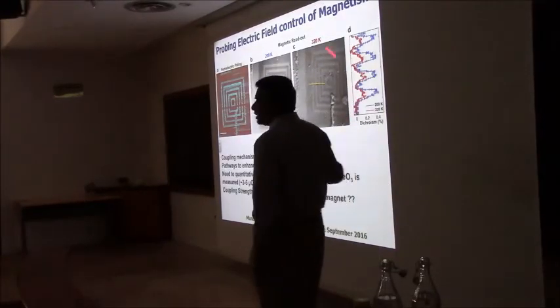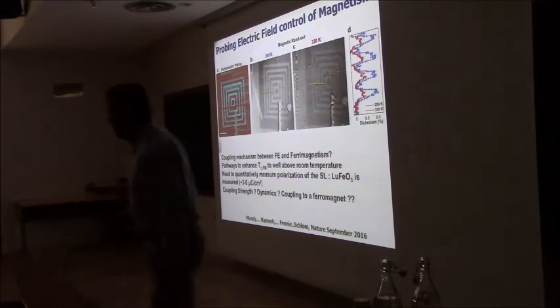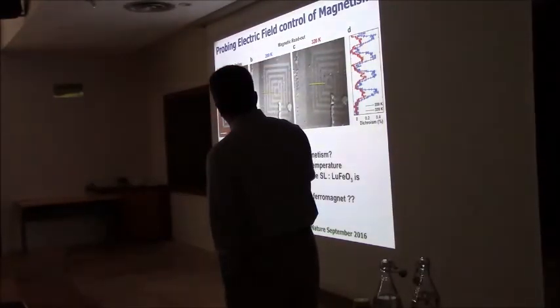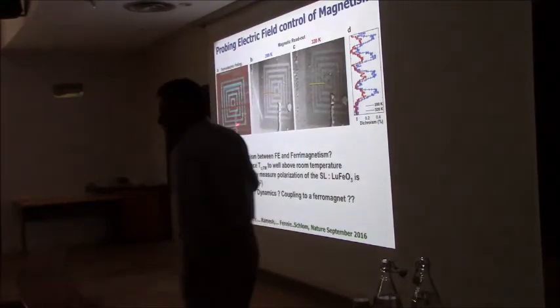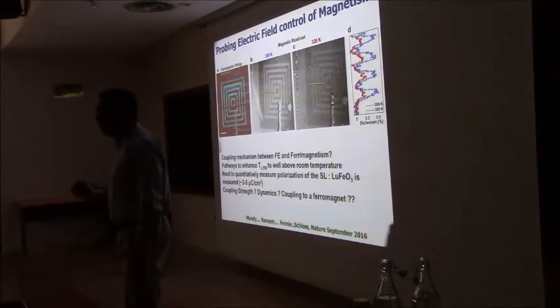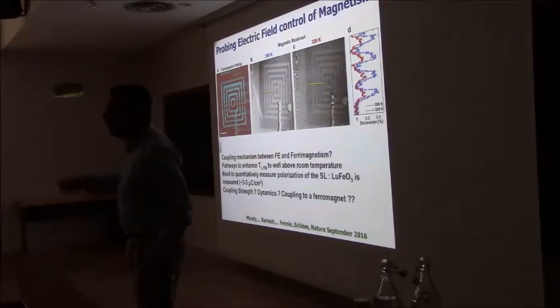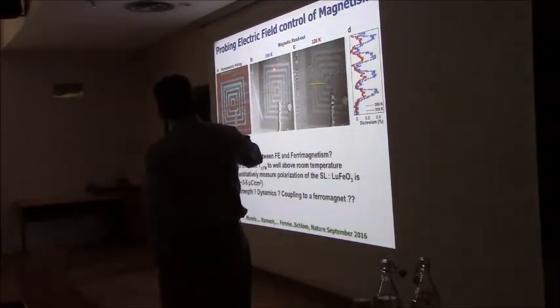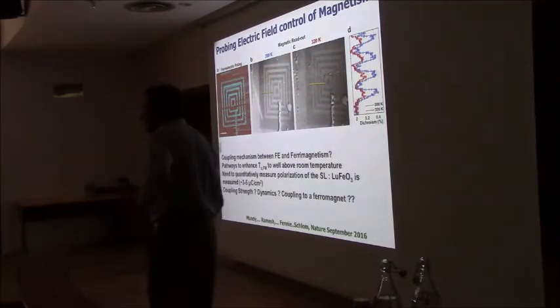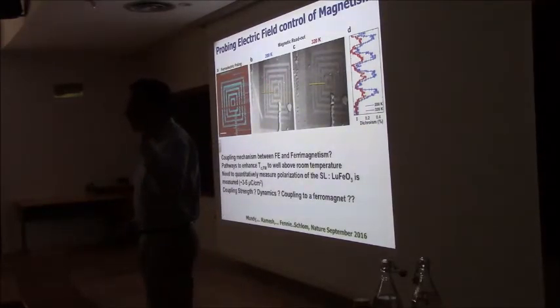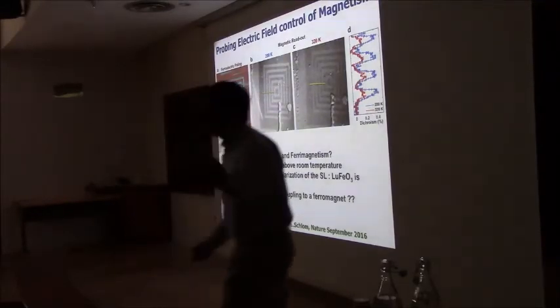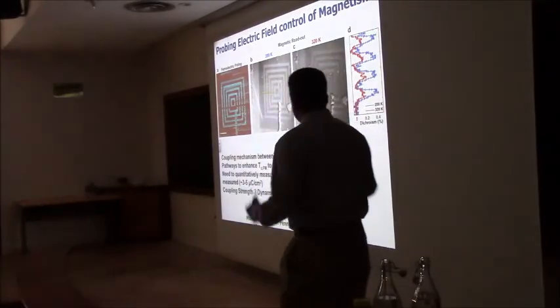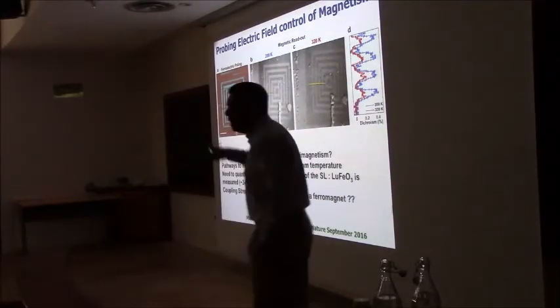Now this experiment took us a long time to do. It took us about 9 months to do this experiment, where we wrote this pattern and went back and imaged the magnetism using, again, circularly polarized X-rays, looking at absorption of the iron edge. And what we saw at 200 Kelvin very clearly, barely there, not there around room temperature, is that we saw the same pattern. It seems to suggest that we have switched the magnetic moment in the superlattice from up to down by applying the electricity. How this happens, we still are not sure yet. We're still trying to figure out the details of how this coupling is mediated through the lattice.